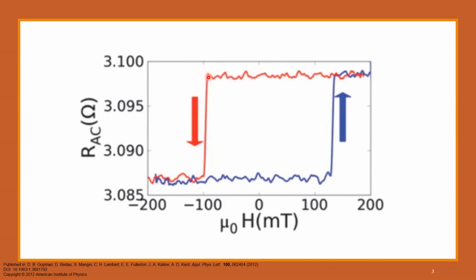The reason magnetization reversal takes place without being oriented at a non-perpendicular angle is that the structure has uniaxial anisotropy perpendicular to the plane, and we apply the magnetic field perpendicular to the plane, which means that it is in the direction of the z-axis. Another observation is that there is an asymmetric switching field behavior.